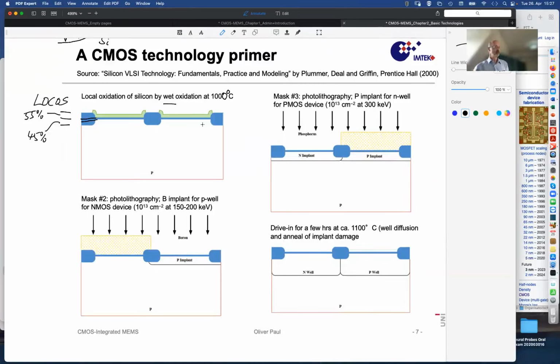Yeah, the nitride has been removed with some phosphoric acid, which does not etch silicon oxide, and now you have this implantation reasonably close to the surface of these boron atoms, and of course you have also implantation of boron atoms, but they are stopped by the photoresist. It's blocked, and not any significant number reaches the silicon below. Okay, then the same thing is done again the other way. So here now we are injecting phosphorus to do some N-doping here. So here we have Nd, and here we have some Na, as it is called in the semiconductor physics jargon, some donor concentration, here some acceptor concentration.